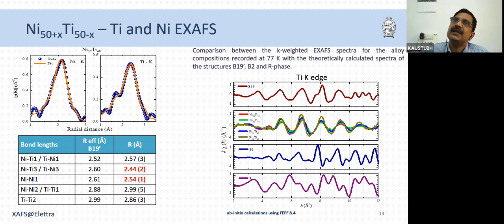And what we did was we used FEFF 8.4 to calculate titanium K-edge EXAFS in all the alloy for all the known phases of nickel titanium. So there are three phases which are known: the stoichiometric nickel titanium, the B19 prime phase, the B2 phase, which is the austenitic structure, and the R phase. And you can see we compared this with the experimental data that we had from our EXAFS studies. And you can see that the experimental data more or less resembles the B19 prime structure. So, okay, our first guess that the structure could be B19 prime or a variation of B19 prime was correct.